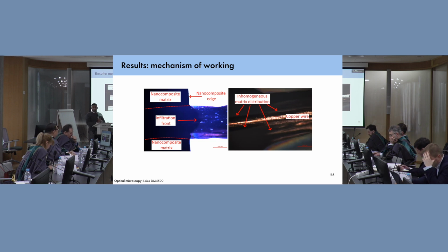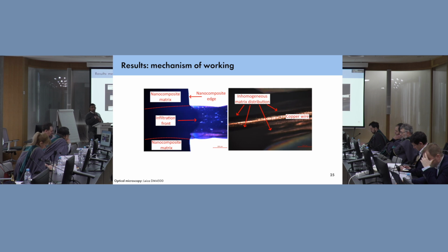couple of interesting findings. First, we were able to see that within the volume, there's a front moving. And it's interesting because we don't see this front on the surface. On the surface, our droplet stopped at this point. But when we looked at it with a little bit more contrast, a little bit more brightness, we could see, okay, it's moving. And then we took a look at the fiber and we see, okay, we have some defects in the volume. And this is the path that's being followed.